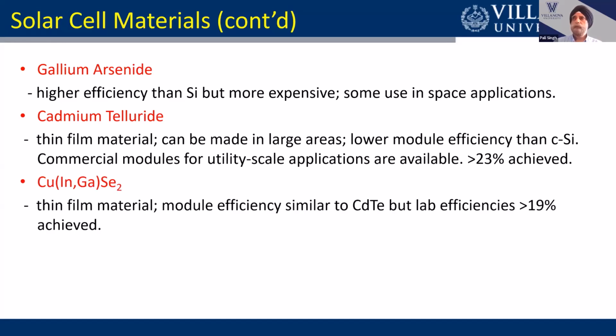Another material that's also a thin film material is copper indium gallium diselenide. Compared to crystalline or polycrystalline silicon materials, which tend to be relatively thick, cadmium telluride and copper indium gallium diselenide tend to be thin materials. So we're talking about 5 microns versus 100 microns in thickness. And again, similar in module efficiency to the cadmium telluride. And there are a few manufacturers of copper indium gallium diselenide solar panels.